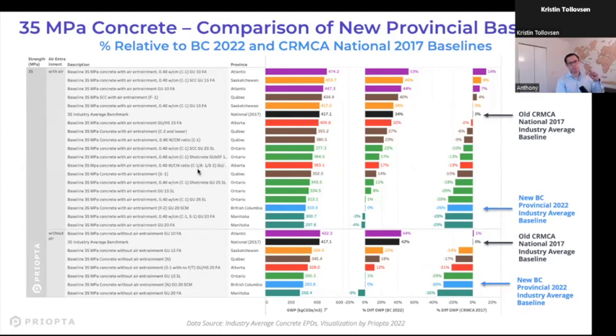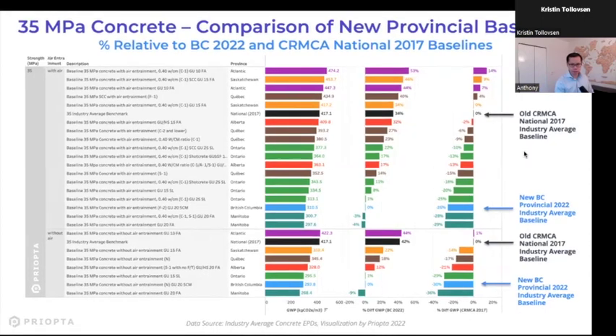Yeah, there's an additional layer of detail for different types of concrete mixes, which is why there are two different baseline mixes in Alberta. But you can see there are some discrepancies between that and the old industry average. For places like BC, that's the slight blue bar, you can see there's a big difference between that and the old industry average. So this is something to be aware of: what is typical practice in different provinces is actually quite different, and that affects what the industry average baselines are for different provinces. So that's something to keep in mind with the release of these new industry averages, and there could be big differences between them.